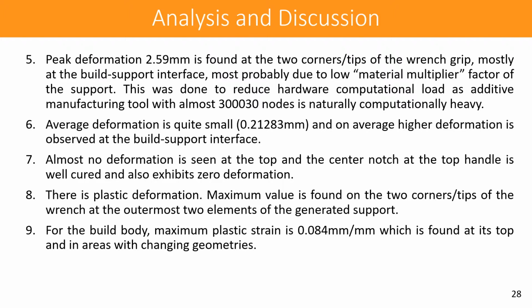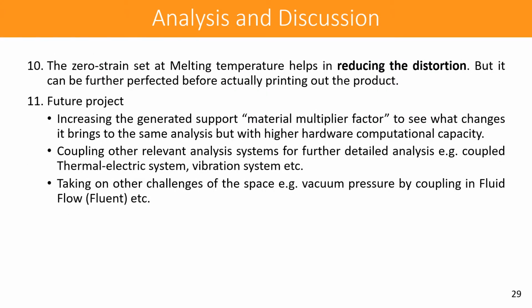Maximum value is found on the two corner tips of the wrench at the outermost two elements of the generated support. For the built body, maximum plastic strain is 0.084 mm over millimeter, which is found at its top and in areas with changing geometries. The zero strain set at melting temperature helps in reducing the distortion, but it can be further perfected before actually printing out the product.